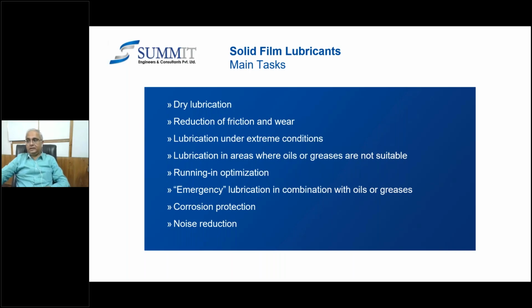Of course, certain elastomers are very susceptible to oils, or are not good for oils. If I come across a situation where I am using those oil seals or elastomeric material, and they are going to be exposed to oil, then I must have better results. So another reason for dry film lubrication is that for such elastomers, I should be able to use these solid film lubricants to address the oil resistance part of it.